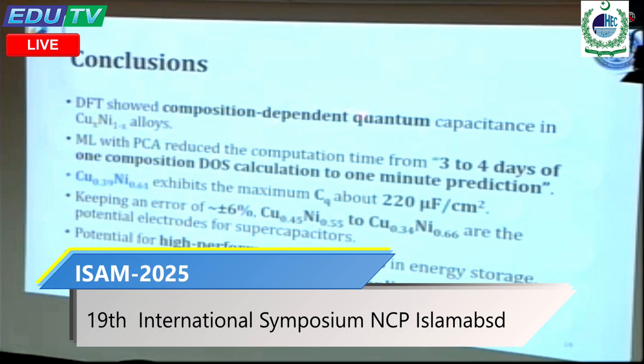In conclusion, DFT showed composition-dependent quantum capacitance in copper nickel alloys, and machine learning with PCA reduces the computational time from, on average, 3 to 4 days for one composition of DOS calculation to 1 minute of prediction. Copper 39% and nickel 61% exhibits the maximum quantum capacitance, about 220 microfarad per centimeter square. If we keep the error in mind, which is plus or minus 6%, then this range of compositions are potential electrodes for supercapacitors. This method is also promising for higher performance supercapacitors in energy storage, and bridges theory and application.